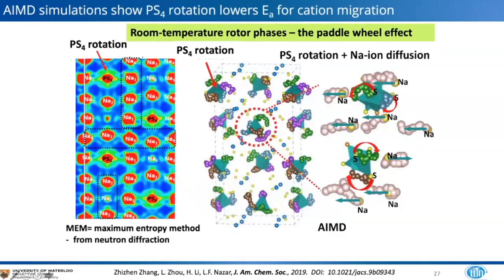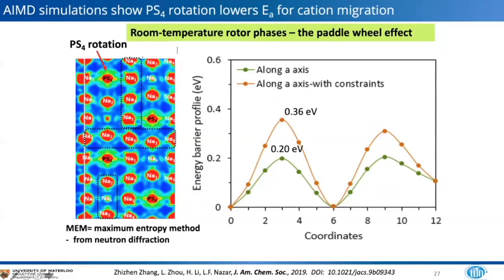So coupled with the MEMS, which I already showed you, this is the rotation of this PS4 group. So coupled with the MEMS, we carried out these AIMD simulations at a variety of different temperatures, and we're actually able to see the onset of this paddle wheel effect. So this is just a snapshot, a 1 picosecond snapshot that shows that as this polyanion is rotating, the sodium is moving from one position to another in the lattice. And so these two processes are coupled. If one pauses or one artificially pauses the motion, the activation energy for that transport, the energy barrier, goes up, increases to 0.36 electron volts, whereas without constraints, it is significantly lower of about 0.2 electron volts. Now this is a little bit of an artificial imposition upon the calculation, but still it shows the importance of the polyanion rotation to lowering that activation barrier for transport.